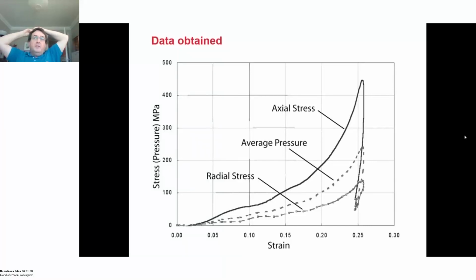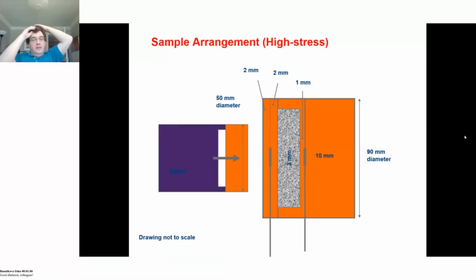You can repeat it with different degrees of water being added, with different particle sizes, etc., and get a series of responses. You can then take your sample arrangement for shock impact, and here we have a system where we have a copper holder with a 3 millimeter thick layer of sand in it, and we're striking it by a plate impactor coming in at up to several hundred meters per second. It hits the front of the target, and we have manganin stress gauges, which I mentioned in tutorial 2, to record the stress in the direction of impact before the sand layer and after the sand layer.